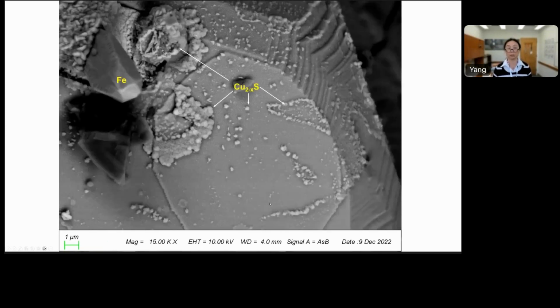And zooming again, those copper sulfides can be really nanocrystalline or slightly larger. Some of them have this kind of bladed morphology, and some of them seem to be clumps of multiple grains. We also see an iron metal grain protruding from the iron sulfide grain too, but this is not always the case. In this case, we do have an iron metal grain.